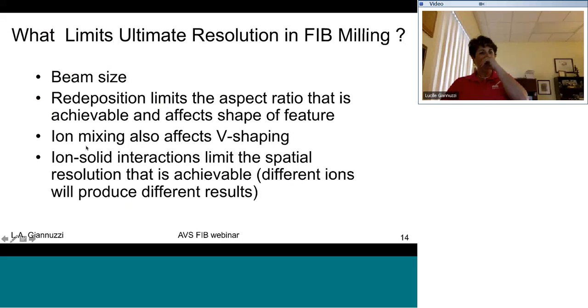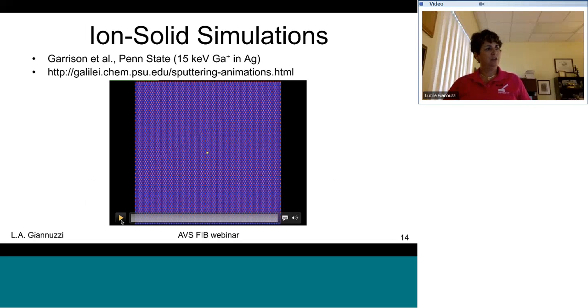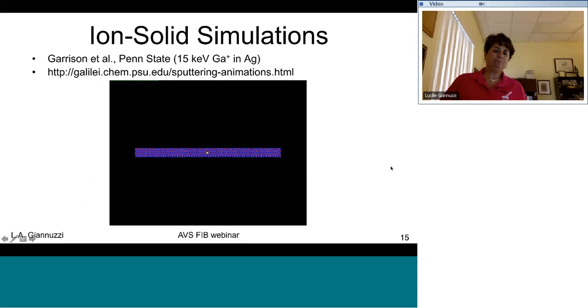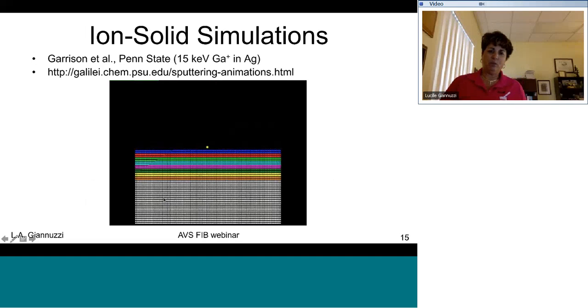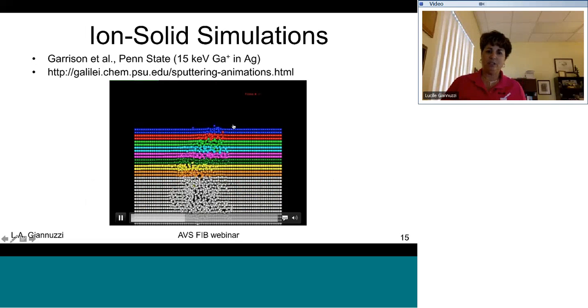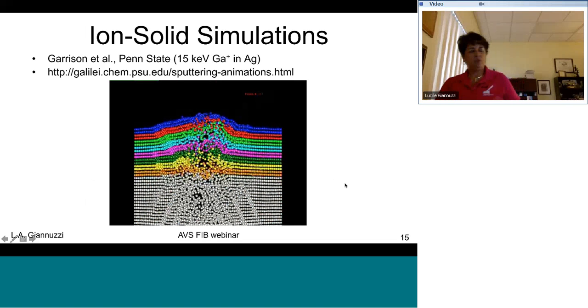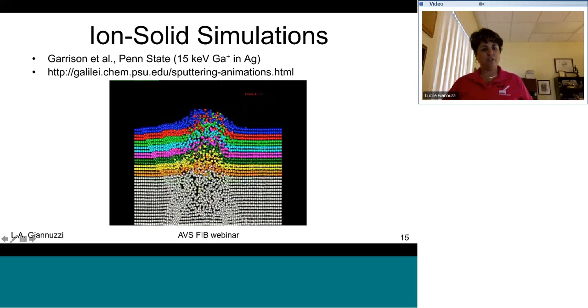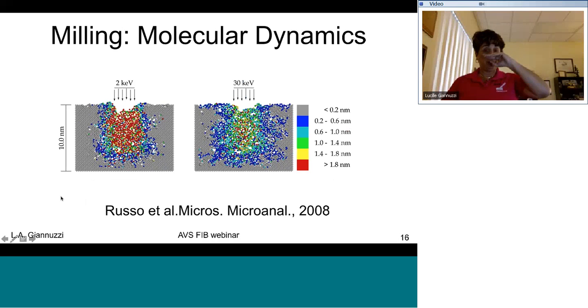Okay, so again, we hit on this before: what limits ultimate resolution in FIB milling? One, the beam size, of course. We talked about redeposition. This limits the aspect ratio that's achievable and also affects the shape of the feature, as I showed you earlier. By just milling the same pattern in different ways, you'll get very different types of shapes. Ion mixing also affects the V-shaping, as well as the ion-solid interactions. Remember, I just showed you this movie earlier that showed when you've got an incoming ion, this can generate sputtered particles at some distance from where the incoming ion is. There goes the particle. And so you might not be able to generate, for example, a certain size hole in a certain material, but you can generate it in another material.